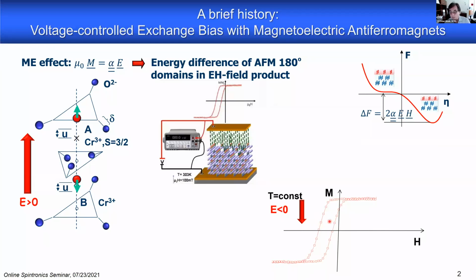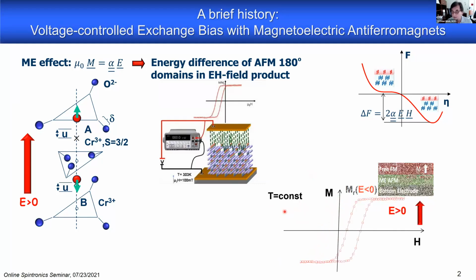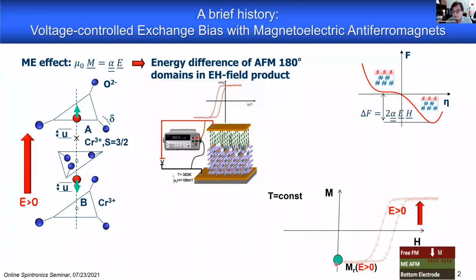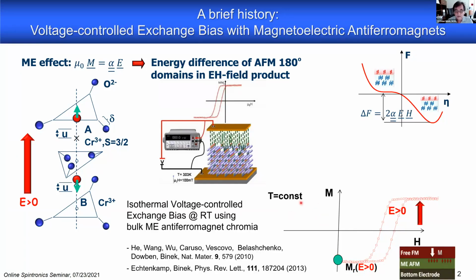I show this here in the cartoon. So this is a hysteresis loop of that ferromagnet, and you apply an electric field of one particular orientation, you get the ordinary negative exchange bias, but then you flip the sign of the electric field. And by doing so, in the presence of a magnetic field, you switch the orientation of all the spins in the antiferromagnet. You 180-degree flip them. That in turn flips the boundary magnetization, and with that, the sign of the exchange bias changes, and you go to positive exchange bias. And now you see, based on these remnant states here, you can use that, if you like, as a state variable, as bit information in devices. And this is a cartoon.